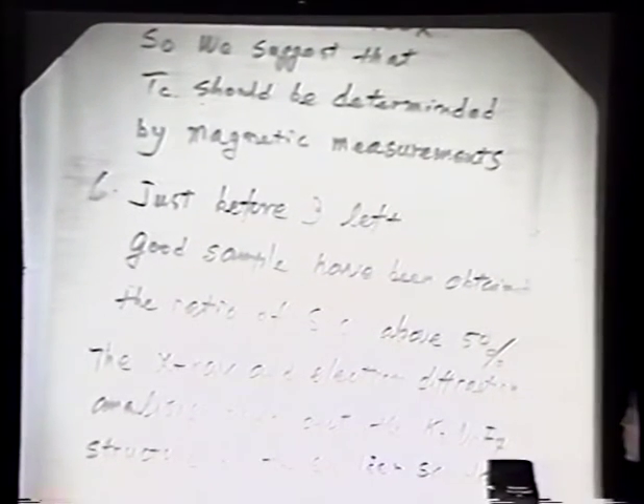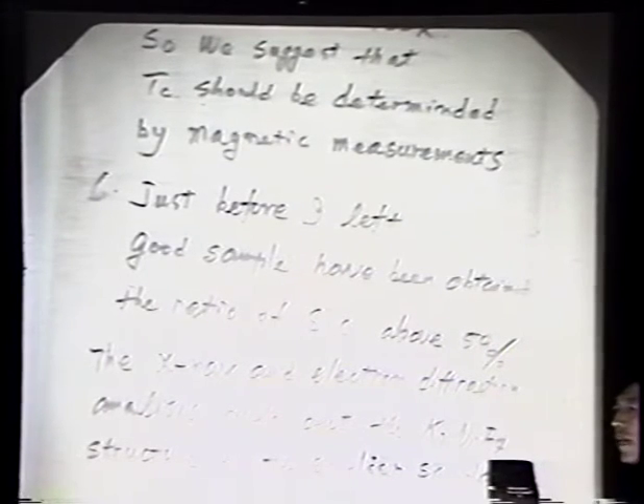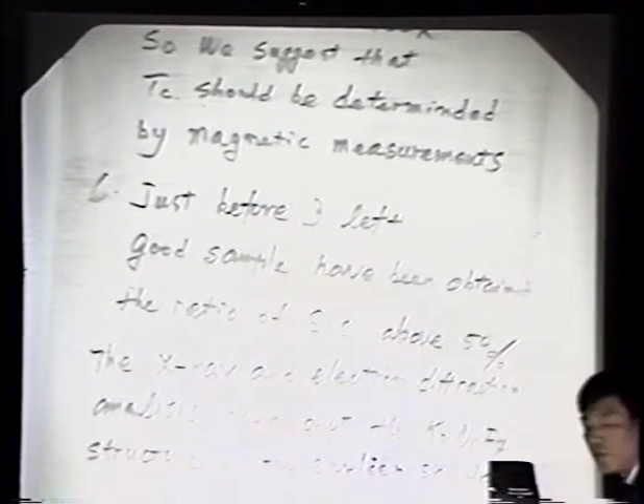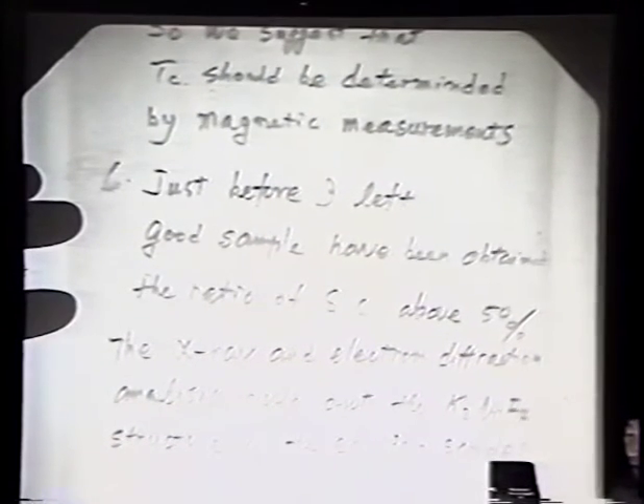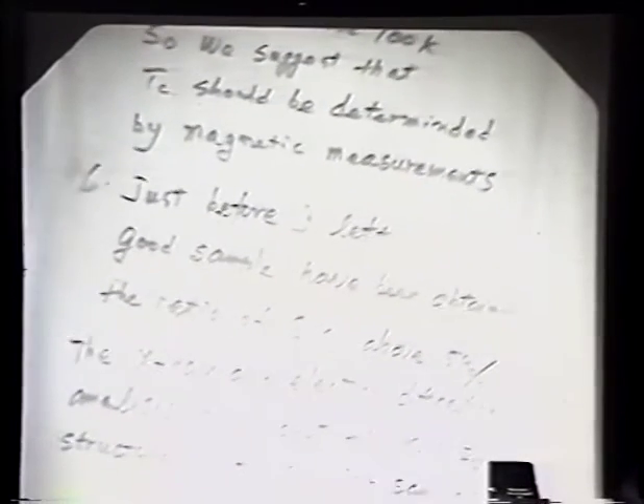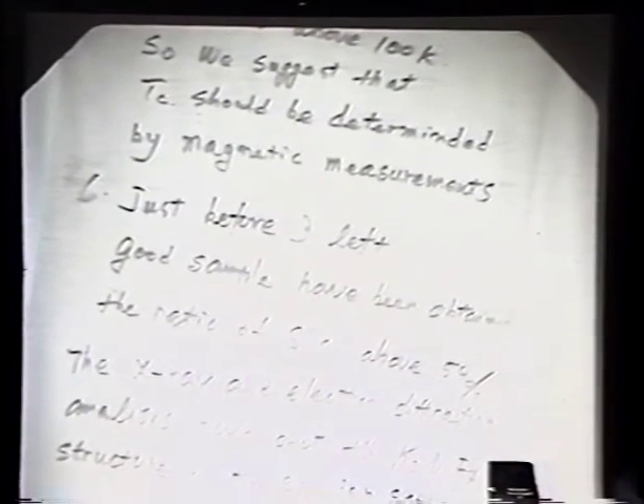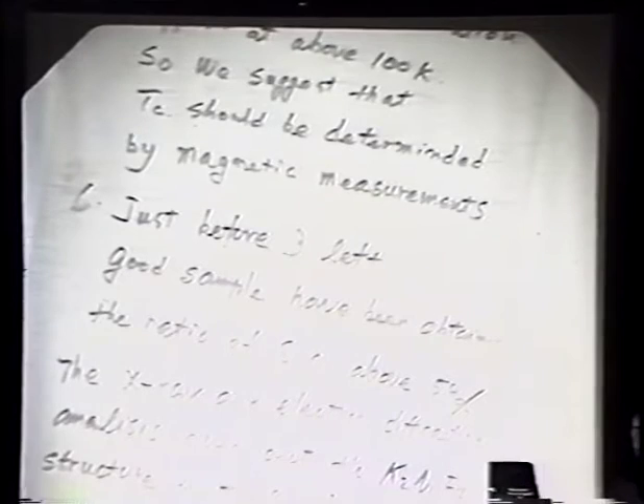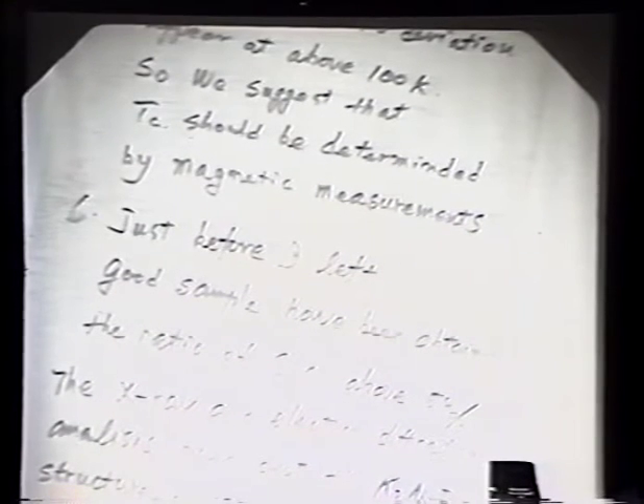Just before I left, a good sample was obtained. At the beginning, the ratio of the superconducting phase to the whole volume was just about 10%, with samples without a multiply connected region. But before I left, we got new samples in which the ratio of superconducting phase is more than 50%. So I show the results like this.